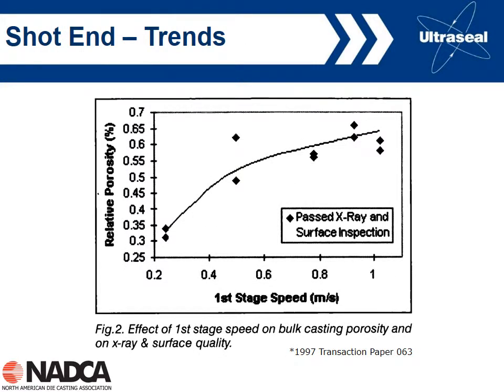So let's talk a little bit about the slow shot velocity, the first stage speed. This is a graph, again from 1997 transactions, with the paper numbers identified here. And what it's showing is the effect of the slow shot velocity upon the relative porosity. We can clearly see that if we want to reduce porosity, we need to use a slower first stage velocity. So a general rule of thumb is the slower the better with the slow shot velocity. Obviously we can't go too slow. We don't want to get too much solidification in the shot sleeve. But in general, the slower the better for the first stage velocity, for the slow shot velocity.